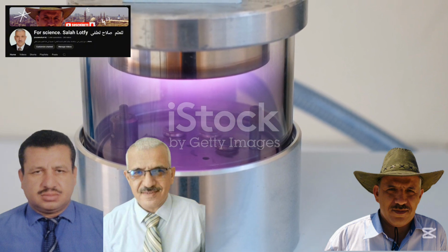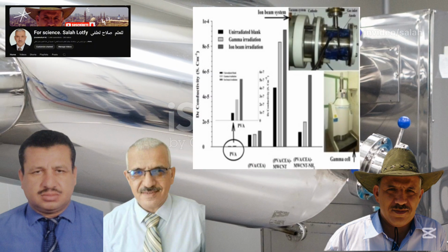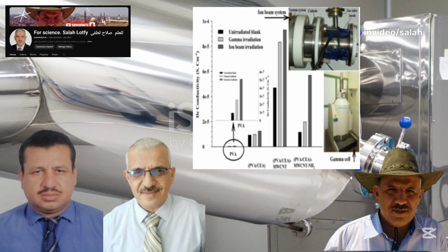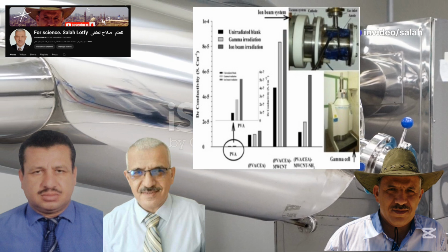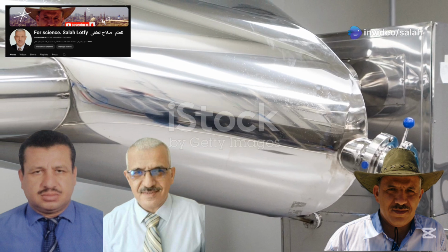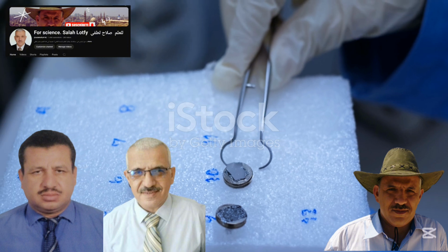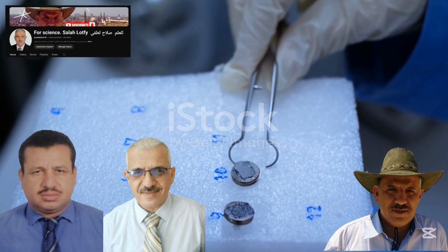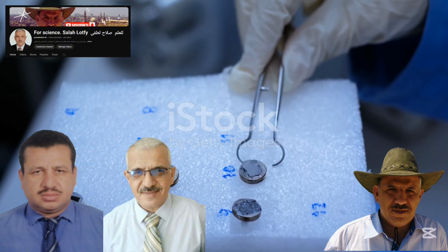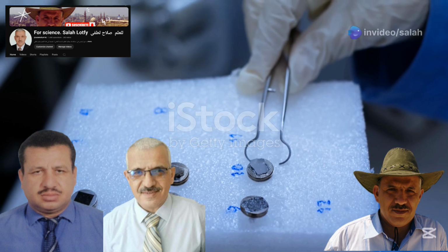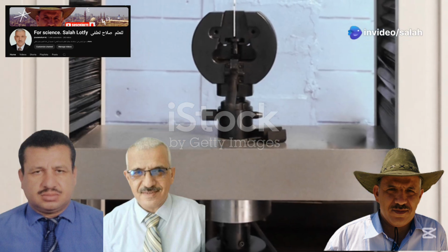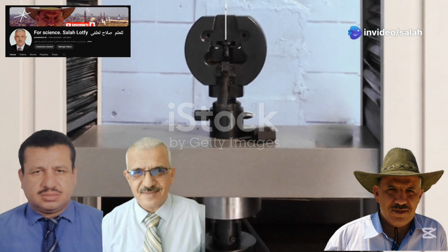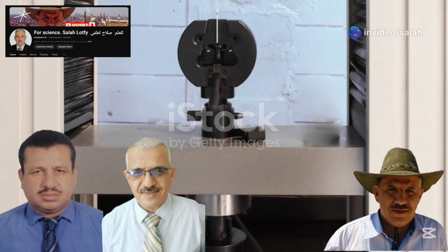Next, ion beam irradiation. We use a cylindrical anode ion source with 4 keV ion energy and 100 µA/cm² beam intensity. The films are bombarded with argon ions at fluences of 2.5 x 10^18 and 3.75 x 10^18 ions/cm². These treatments boost the mechanical, electrical, and thermal stability of our nanocomposites. But how do we know it works?